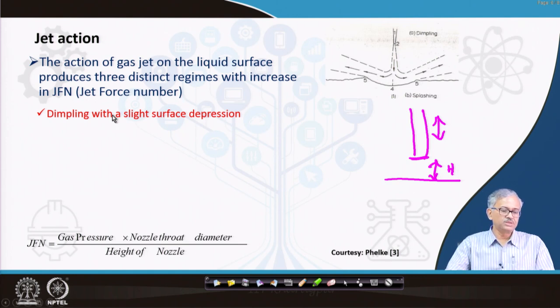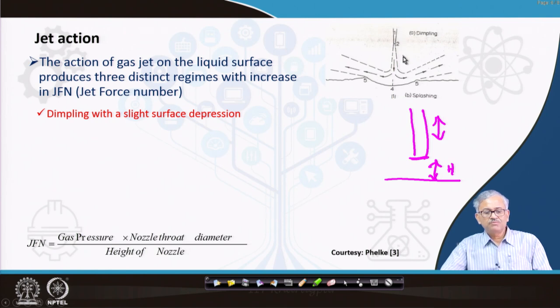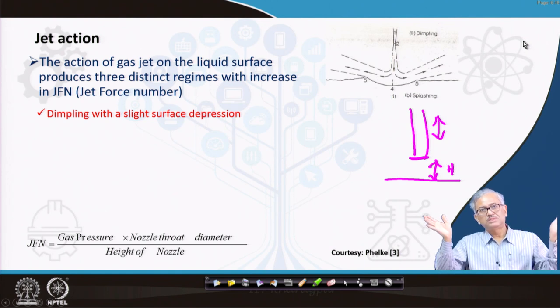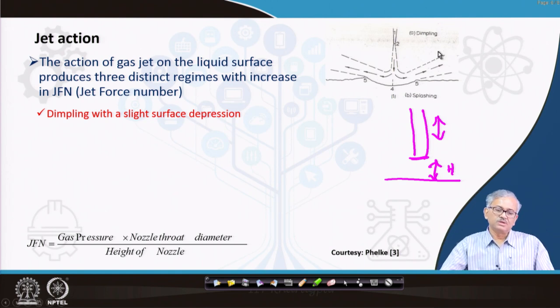One is called dimpling, with a slight surface depression. Here is the nozzle, and whatever the force is, it can form a small dimple, and a lot of splashing of liquid droplets away from it. So a very slight depression is there, and the liquid droplets are ejected across and can directly hit the refractory wall. This is not a very good condition.